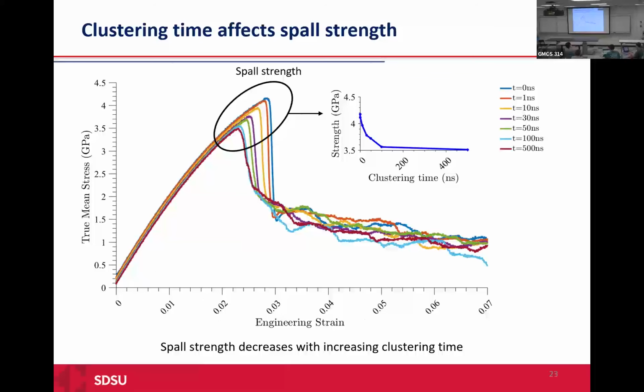After having those shock waves through the material, usually those shock waves are producing a super concentration of vacancies. If given enough time, at those shock loading temperatures and also the state of stress, they might just cluster together and form something like nanovoids. Yeah, there's a lot of mechanisms that will do that. So it's fair to say the loading induces the super concentration of vacancies and also the process of coalescence. Yes, the tensile part of shock loading.